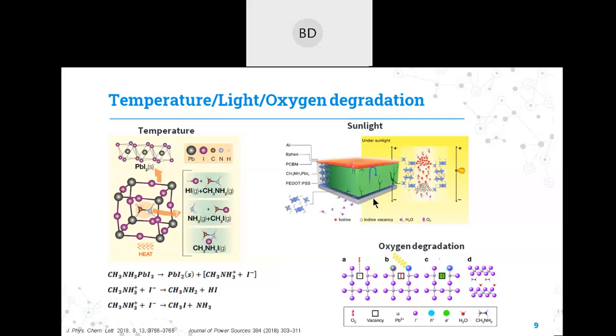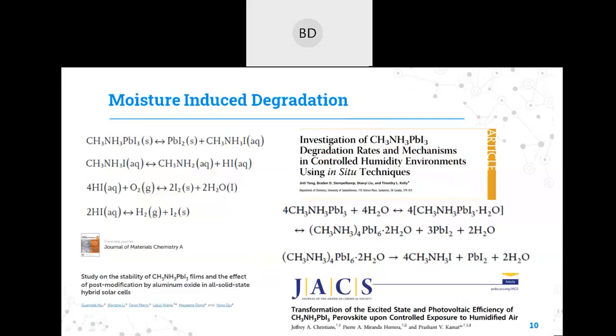Now, among all these factors, as we discussed earlier also, moisture is the most important degrading factor. Some degradation mechanisms due to humidity have been reported. Some say that the perovskite can disintegrate into lead iodide and MAI, and some say that it goes through a hydration step. So there have been some reports, but still there is a lack of understanding of the governing degradation mechanism of perovskite.